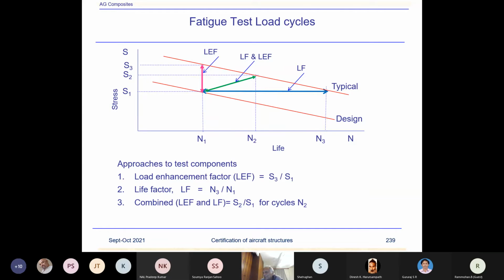But as I said, generally the rough guidance is maybe about 10 to 15%. The reason why you don't want to exceed around 15% is that it puts the metallic structures at risk of failing. You have the metallic hinges, and if you are overloading them, there would be components which may fail prematurely. So this is a balance between each of the component failures, the modes of failure, the life and the load enhancement factor. In a structure, based on the coupon test data, we try to evaluate these factors and then apply them to the component test.